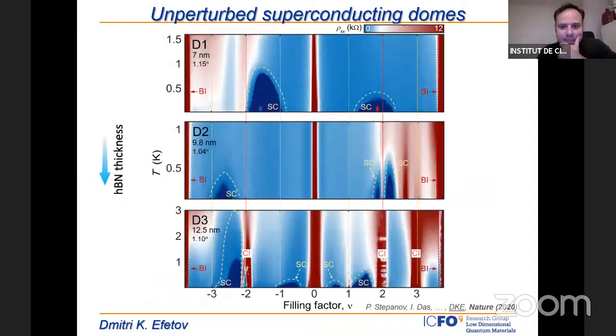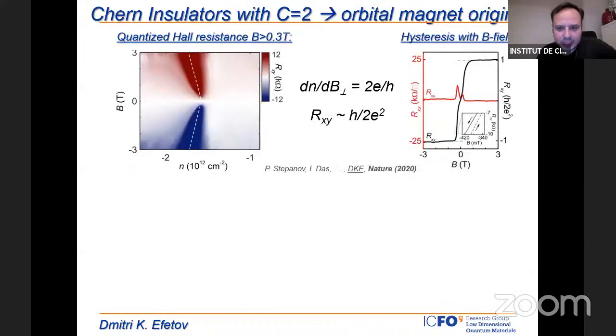Okay, so all right. And then I also want to mention, this is a little bit of a gear change now. This story was about correlated insulators and superconductors, but I really want to also mention the topological magnetic states. What we also see in the very same devices, and we really see these features quite robustly now, is that we see them very close to zero magnetic field. And actually other groups, including us now, there's a paper in preparation, we also see those states at zero field, so basically at zero magnetic field.